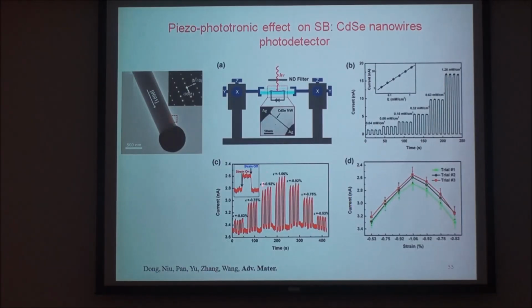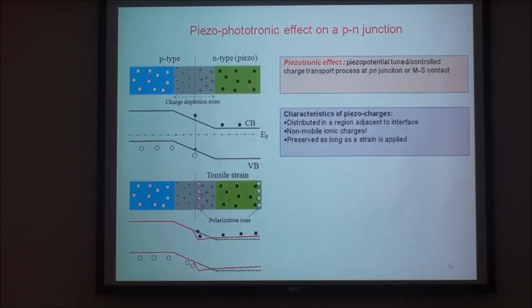So in reality, these two cases have to be optimized. And we found this case. You see, this is the sensitivity of the detector here, and only at a particular strain, the detector reached the maximum, because the barrier height at this strain gives the best performance.